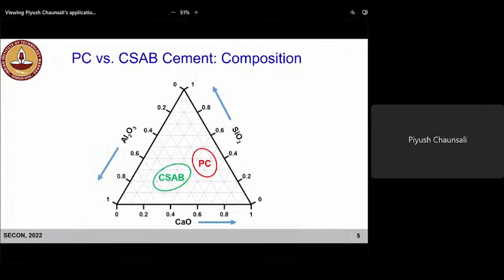Again, this ternary diagram shows a comparison between PC, which is Portland cement, and CSAB. And what you see, CSAB cement has more alumina. So in this direction, the alumina content is increasing. In this direction, silicon content is increasing. In this direction, calcium content is increasing. So we can see generally for CSAB phase composition, we are closer to this corner. So it has more alumina and less calcium. So less limestone is required to manufacture this cement. So that also results in reduced carbon footprint associated with the manufacturing of CSAB cement.